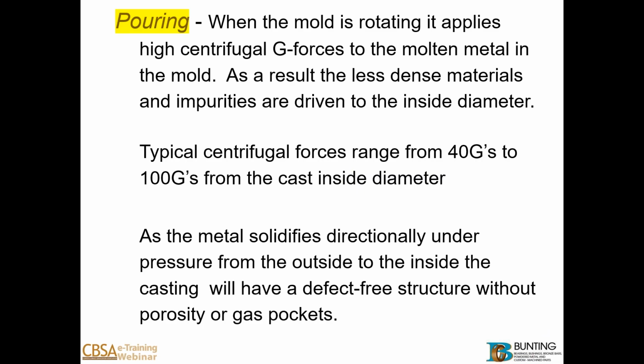When the mold is rotating, it applies high centrifugal forces. Again, in our world, we talk about the G's. We talk RPM and the resulting G's, G force. As a result, the less dense materials and impurities are driven to the inside diameter of the casting. So if you can envision material being poured into this die, spinning at a very high rate, the lighter impurities tend to stay to the inside of the casting.